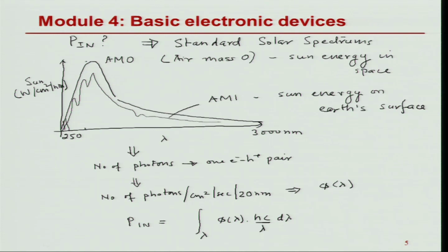Now what are these numbers generally like? It depends on which technology or which semiconductor we are going to use. Silicon is the most common one, and the one which we have also discussed extensively. It almost constitutes 90% of the solar cells which are fabricated even today, and its maximum efficiency can be something like 25%, if everything is done in a proper way. But commercially what you get is somewhere between 15 to 16%. So there is a gap between the theoretical efficiency you can get and what one manufactures, and we will try to see why that gap is there and how one can improve it.